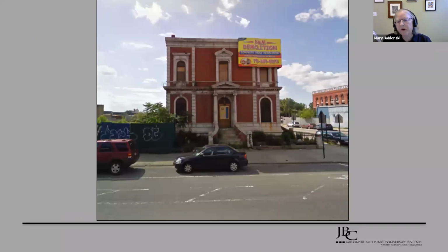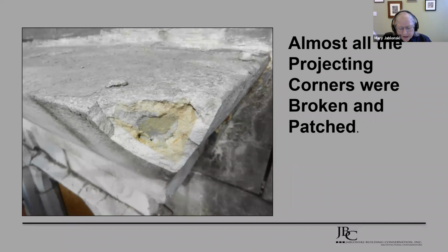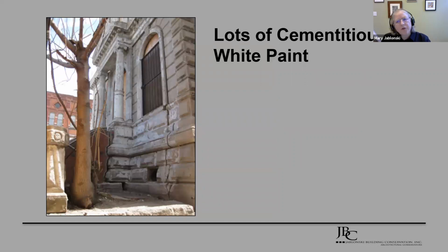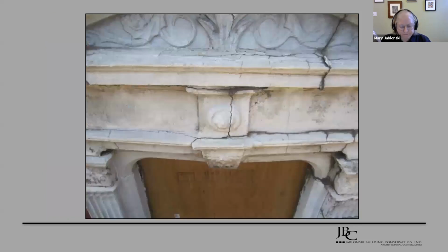There was still brick face on two facades. You can see some of it from the older one. And actually there was this interesting phenomenon that we also found here, and that was almost all the projecting, in fact, all the projecting corners were broken or patched. And possibly this was because they were exposed on four sides, but it appears to have actually been a weakness in the casting of these units. There was also a lot of cementitious white paint on any of the cast stone units that had been left exposed. And just to top it off, there was bituminous coating on the back of the building.